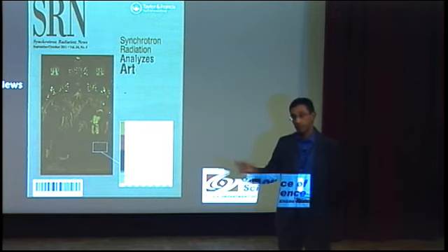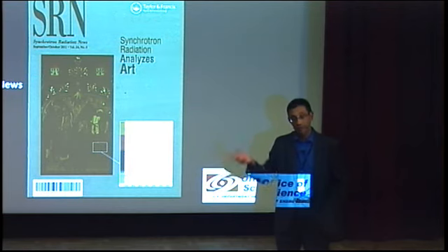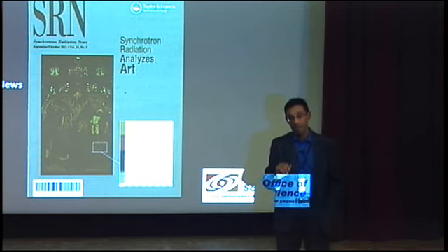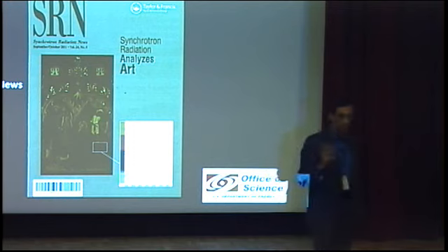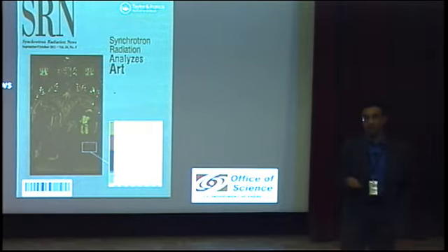So what we try to do is we try to scan the painting, for example. We try to scan fast enough. So we have high photon density, so we can quickly scan across a surface. As a result, we minimize the exposure time, and we minimize the radiation damage. But we have to be careful with that. Yes, that's right. It might be an issue. As long as we have minerals, inorganic materials, inorganic pigments, it's fine. It's very stable. If we have organic materials, it's a different story.